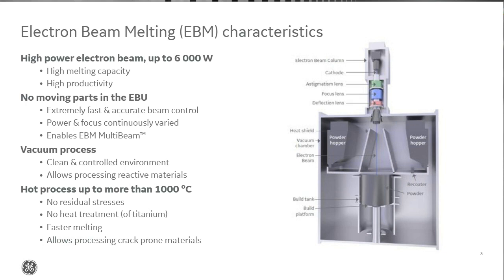EBM is also very well suited for materials which are sensitive to cracking, for example, brittle material. One of the reasons behind this is that we are carrying out our entire process at an elevated temperature, and that temperature is very much dependent on which material you process. In the copper case, you would have a surrounding temperature of around 300 degrees. If you go to a titanium alloy, you might be at 600 degrees. And if you go to very, very temperature resistant materials, it might be about 1,000 degrees.